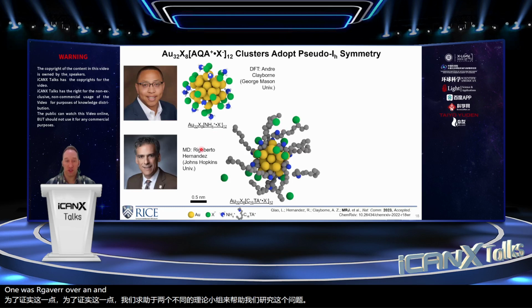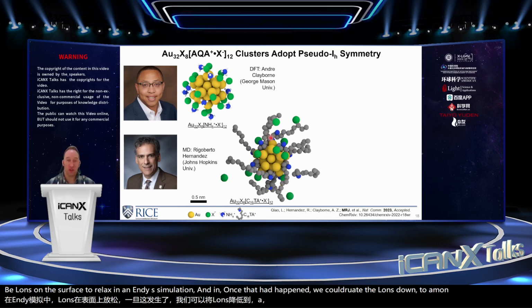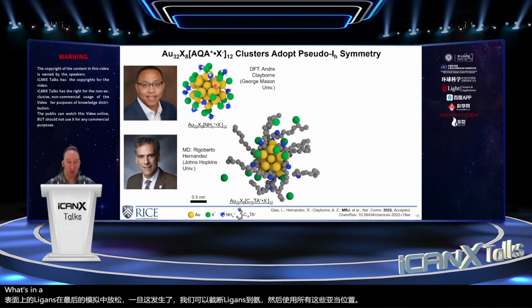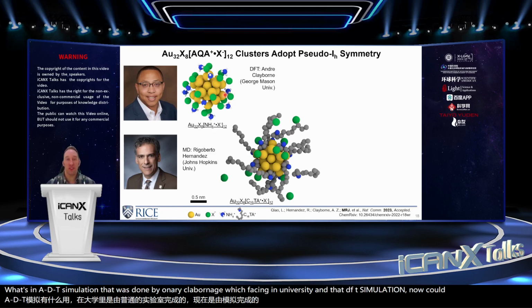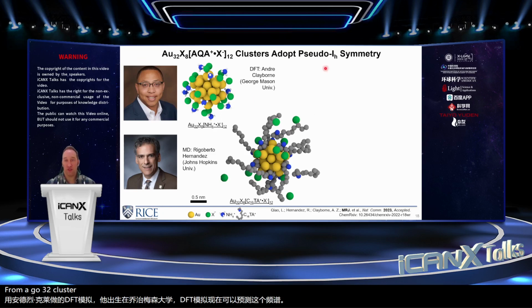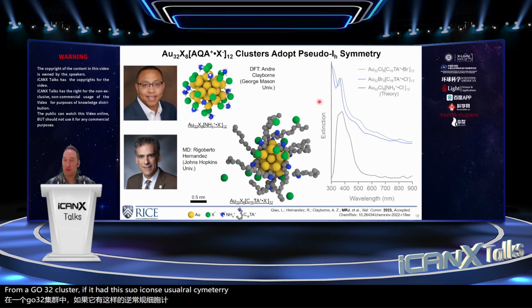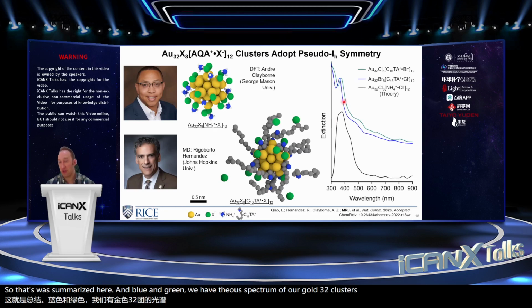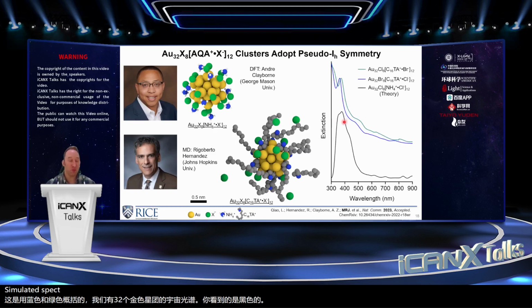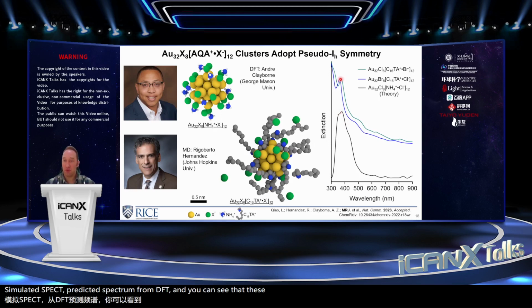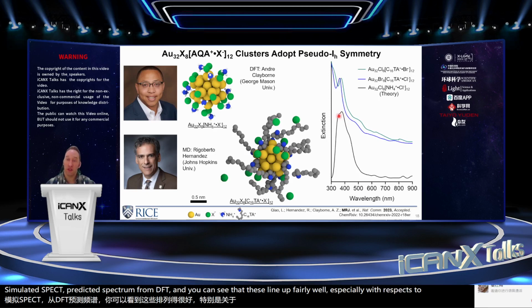One was Rigoberto Hernandez at Johns Hopkins, who fixed the positions of the gold atoms in the core and allowed the ligands on the surface to relax in an MD simulation. And then once that had happened, we could truncate the ligands down to ammonia and use all of those atom positions as inputs in a DFT simulation done by Andre Claiborne at George Mason University. That DFT simulation could predict a UV-Vis spectrum for a gold-32 cluster with this pseudo-icosahedral symmetry. So that's what's summarized here. In blue and green, we have the UV-Vis spectra of our gold-32 clusters. In black, you're looking at the predicted spectra from DFT. And you can see that these line up fairly well, especially with respect to the strongest electronic transitions.